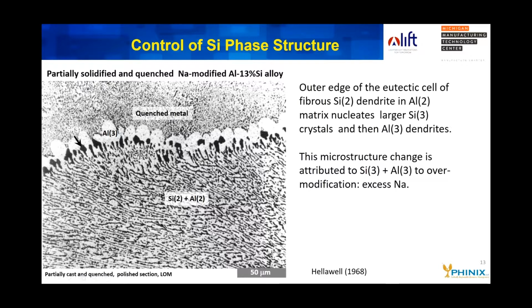Now, in this particular case, the modified structure is in the form of a very fibrous silicon dendrite with submicron fiber diameter. And on quenching, it was shown that the outer part of it contains coarser silicon particles and aluminum dendrites on the outer edge. Hellawell, who did the work, attributed those coarser particles forming later and the aluminum dendrites to over-modification, i.e. too much sodium added to the structure.